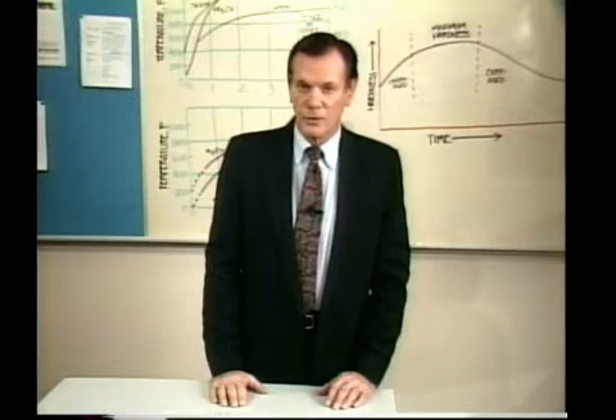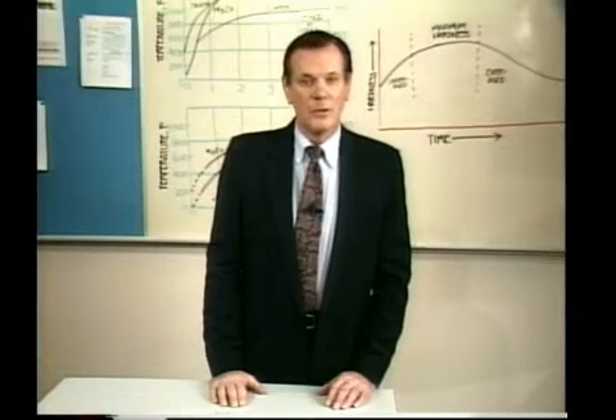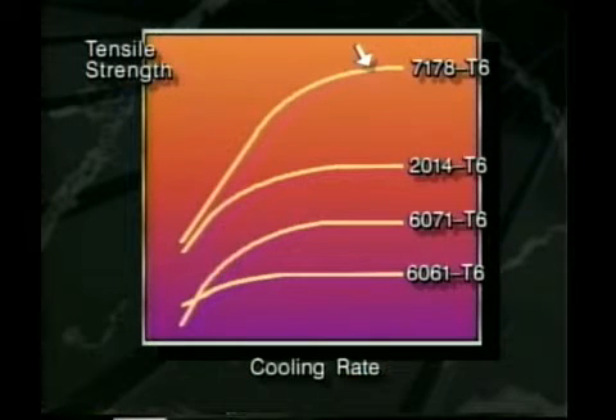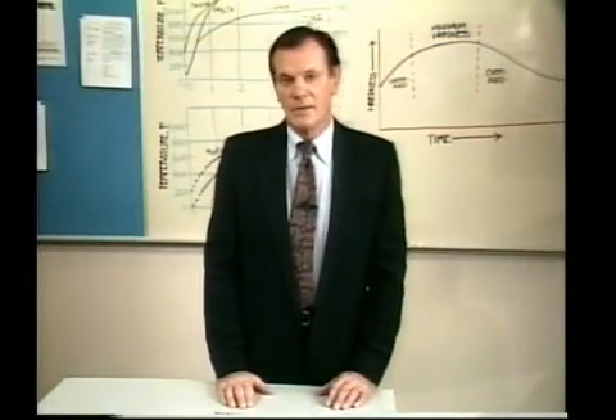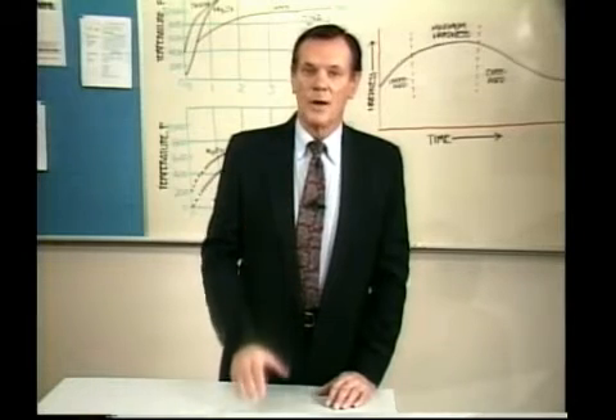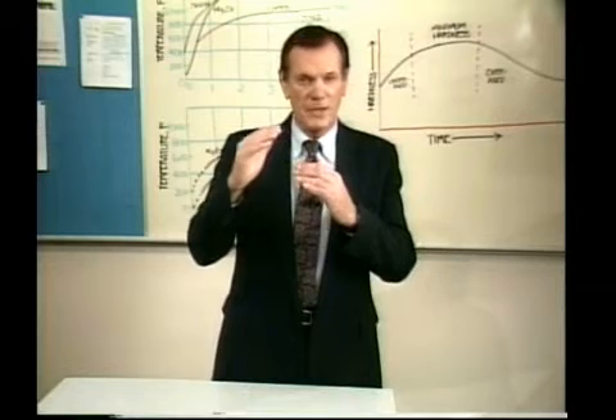The level of properties achieved and the sensitivity of various aluminum alloys to different quench rates varies depending on the chemical composition and the working history of the part. As noted by the arrows in the illustration, the critical quench rate for 7178 alloy is extremely high, approximately 1,000 degrees per second, and its quench sensitivity very high, as noted by the rapid loss of tensile strength at quench rates below 500 degrees per second. Inadequate quenching of this alloy will result in much lower properties. From a practical standpoint, the quench sensitivity of an alloy is the controlling factor as to whether or not high properties can be obtained in thick pieces of aluminum.